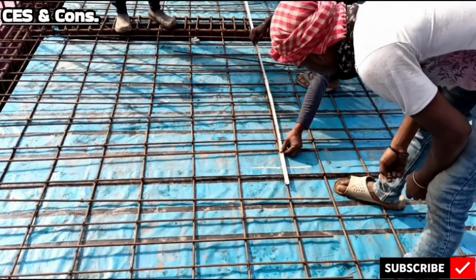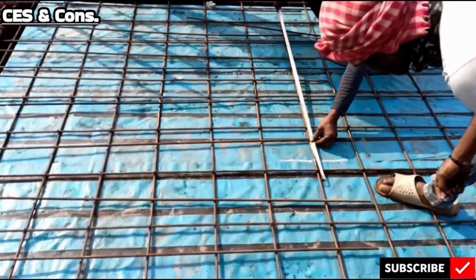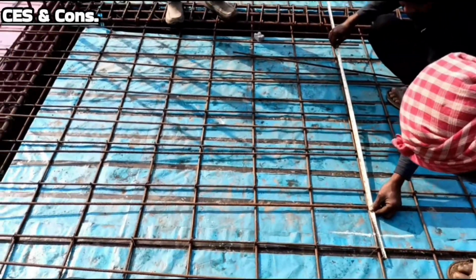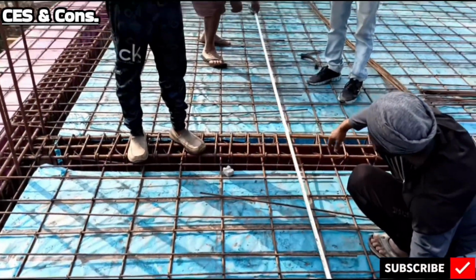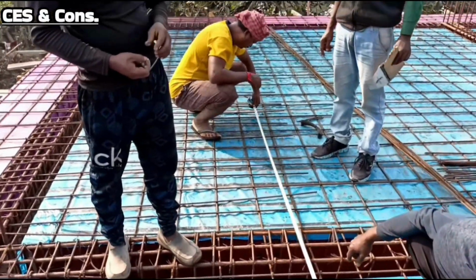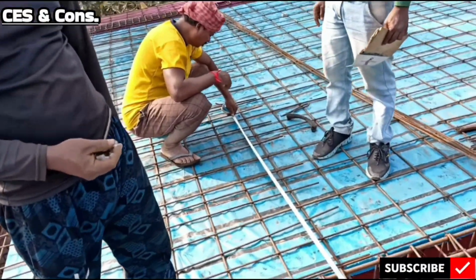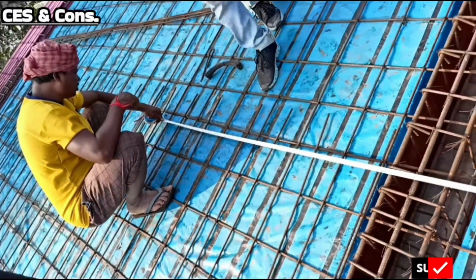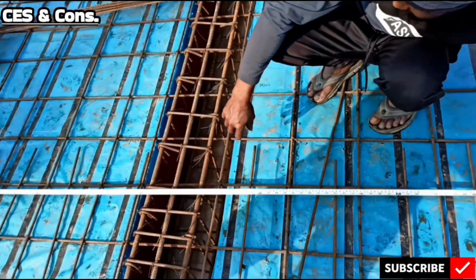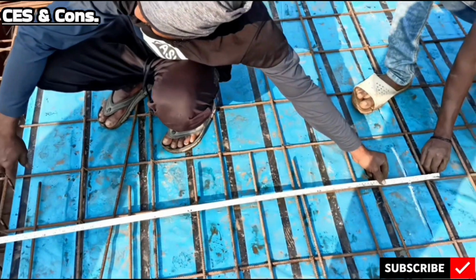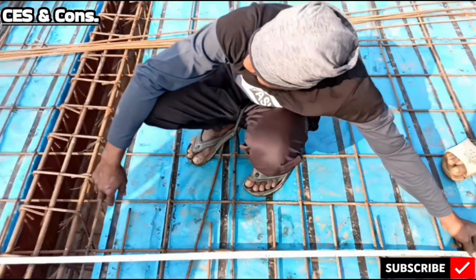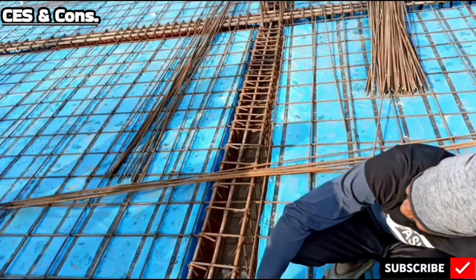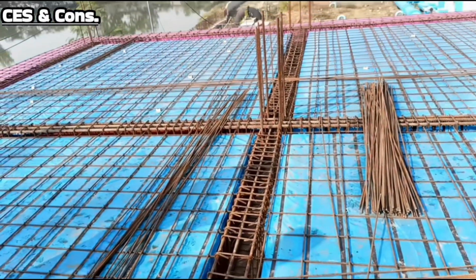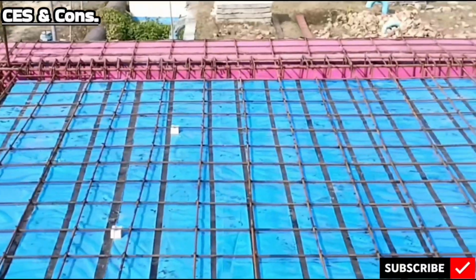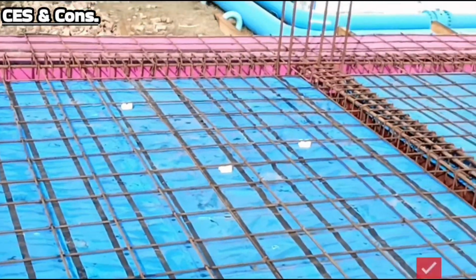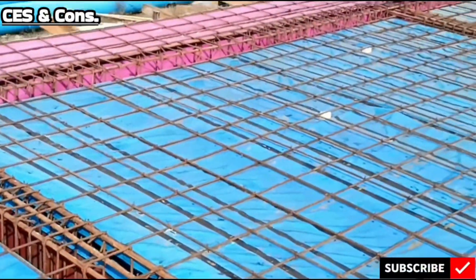Now going to the reinforcement steel. This should be HYSD bars of Fe 500 or Fe 500D as per Indian Standard Code of Practice 1786. This must be rust free, straightened before use. Reinforcement is placed as per structural drawings and Indian Standard Code of Practice 456-2000 provisions. Main reinforcement, that is bottom steel, is provided along the shorter span of the slab. These reinforcement bars resist positive bending moments at mid-span of the slab.